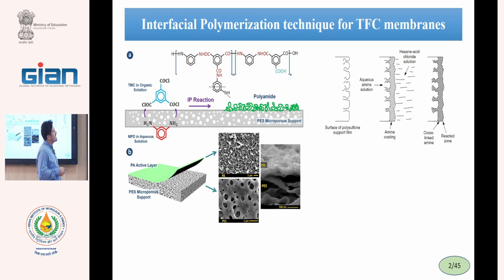For fabrication of this layer, there are many methods that are called surface engineering. And the famous one is interfacial polymerization. That means the polymerization happens between two layers, at the interface of two layers. Therefore, for producing an interface, we need an organic solution and an aqueous solution. These should not be miscible and produce two layers, and the reaction will happen between these layers. Therefore, we call it interfacial polymerization,